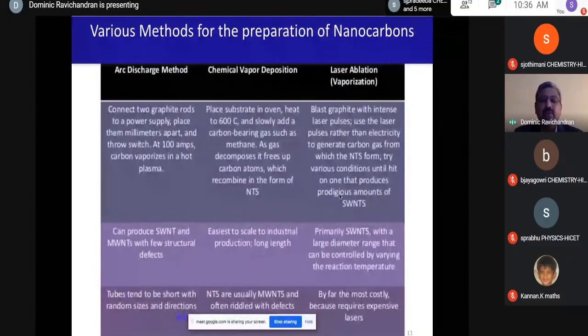When it is with a distance of 1 to 2 millimeter, what we get is a carbon quantum dot or fullerene. But when it is increased from 2 to 25 millimeter, we get the other materials like the CNTs, carbon nanotubes.